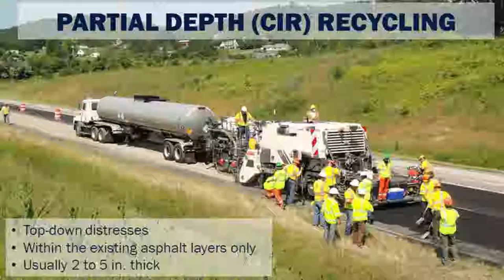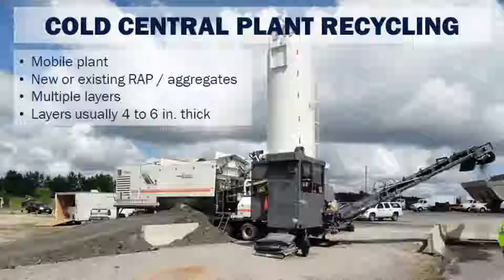All right, so partial depth, Steve went into this. So primarily top-down distresses within the existing asphalt layers, typically around 2 to 5 inches thick. The cold central plant recycling, mobile plant, so mill it off, take it to a mobile plant close to the project, process it, take it back, put it down with a paver. You can do it with any layer. You can take the layers off, stabilize the subgrade, bring those layers back, all that sort of thing. Layers typically 4 to 6 inches thick, the individual layers are. We have been involved in projects where we have multiple layers of the recycled material.